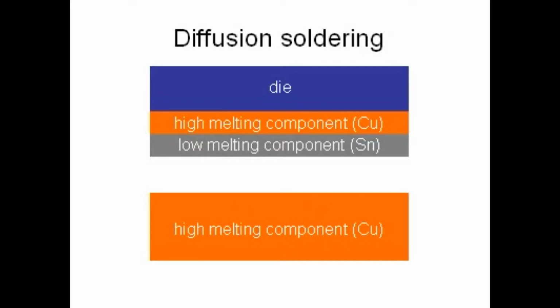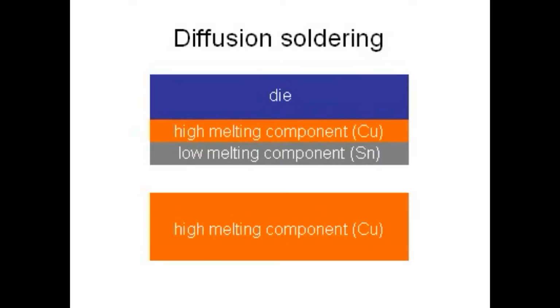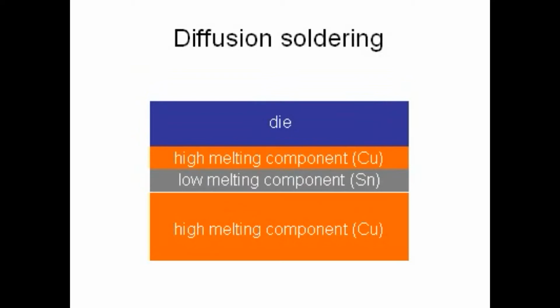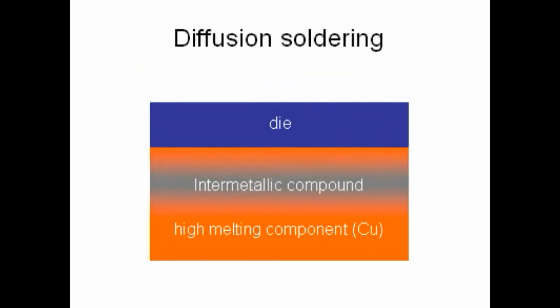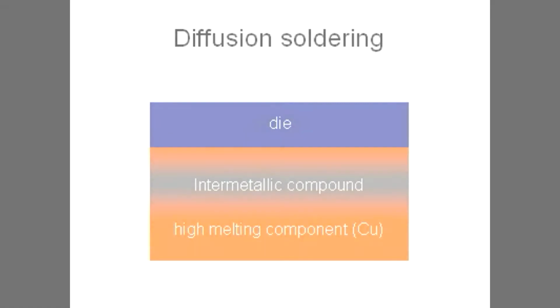For this method, the interconnect material is directly deposited on the wafer backside by either electrochemical plating or physical vapor deposition. It consists of a layer of high melting temperature metal like copper and a layer of low melting solder like tin. When the chip is pressed on the hot copper substrate, the tin is melted and by diffusion of copper an intermetallic compound with a higher melting temperature is formed, so that it is solidifying isothermally.